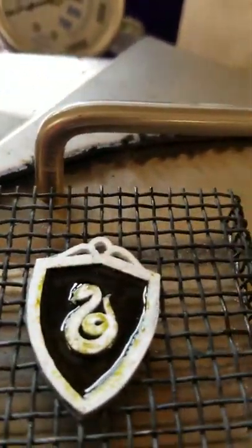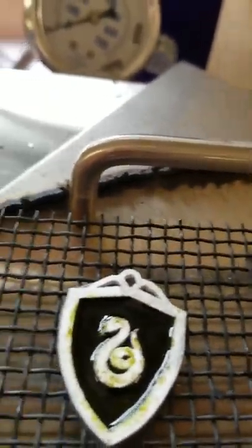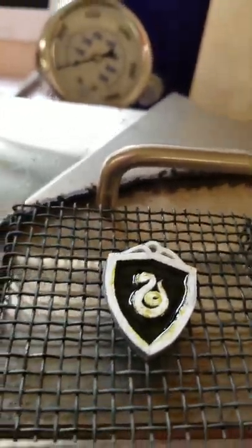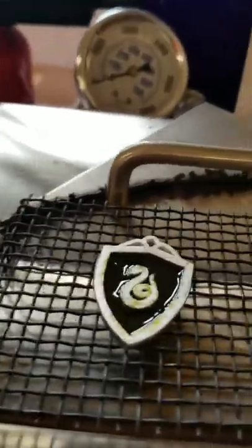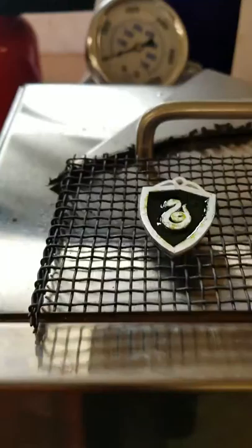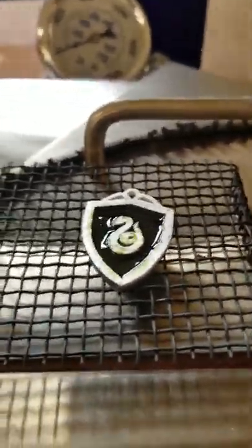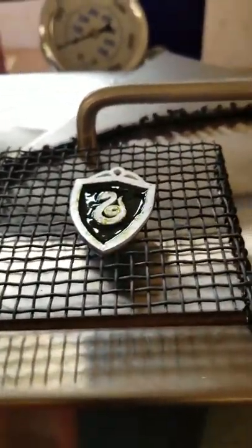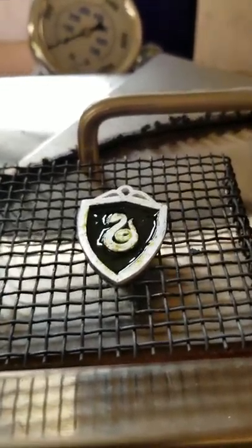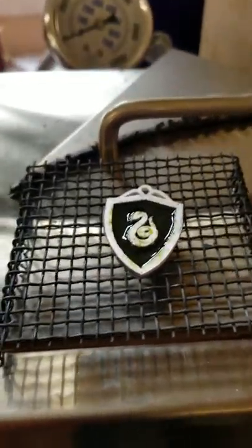And you see, that glass is all melted now. It's really dark, but that'll change as it cools. We leave it on top of the kiln to let it cool slower, because the kiln's really hot. If it cools too fast, the temperature differentials will cause the glass to crack, and our whole process is ruined, and we definitely don't want that. But that is how you do one layer of glass enamel on a piece like this.